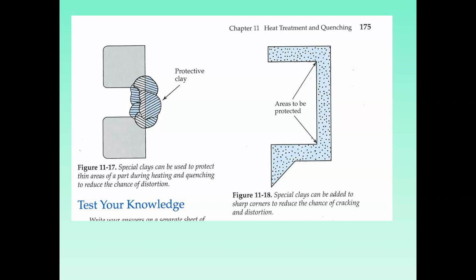How about a sword that is a 1/2 inch at its thickest to 1/16 taper to the blade and 30 inches long? You would only let it soak, you'd only let it heat treat 30 minutes, and you would put clay on the cutting edge.